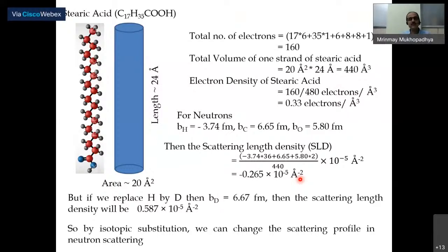But here the importance comes for neutron scattering. You have H, which is minus 3.74. But if you just replace this H by D, then this B of D is 6.67. So what you are calculating here, minus 0.265, will become plus 0.587 for your D atoms. So just replace the hydrogen with deuterium, and you have a lot of scattering from your stearic acid. So by isotopic substitution, we can change the scattering.